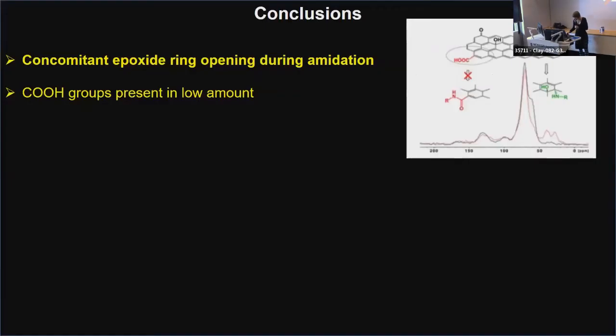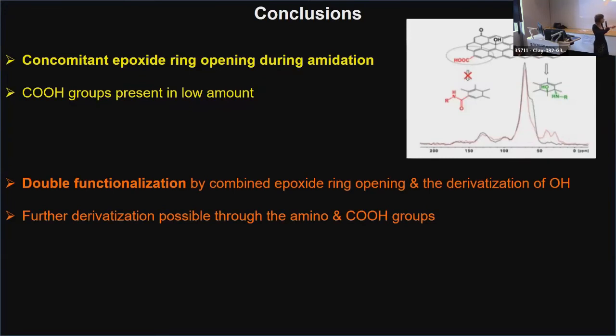So to conclude on this part, I have shown you that in the conditions of the amidation reaction, there is the concomitant epoxide ring opening, which is in fact the main reaction taking place. We have shown by solid state NMR that the carboxylic acid groups are present in a very low amount. We have also designed different strategies for the double functionalization of graphene oxide by combining epoxide ring opening and the derivatization of the hydroxyls. There is also the possibility to further derivatize the graphene oxide by exploiting the amino groups and carboxylic acid groups that we grafted on the surface of graphene oxide. And it is something that we have explored for the conjugation of bioactive molecules.